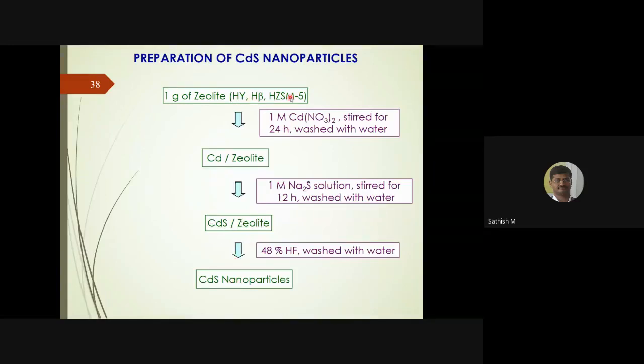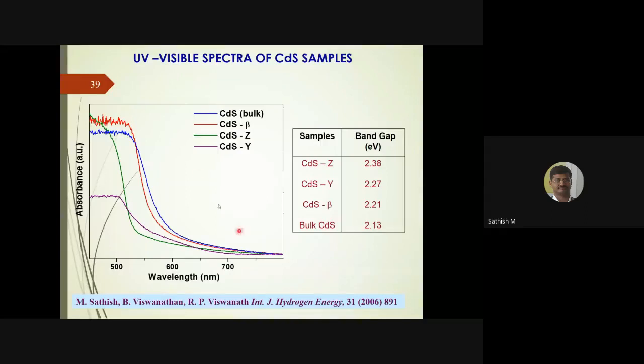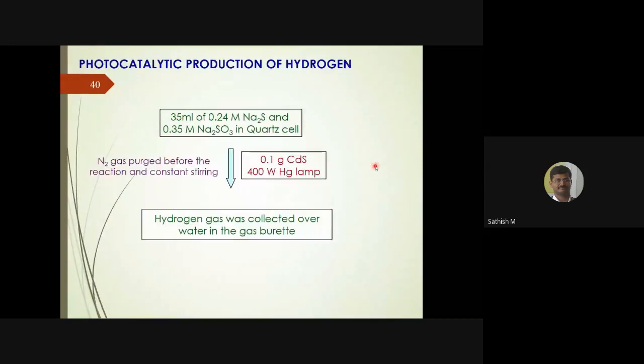So that cadmium sulfide nanoparticle you could get. Depending on the pore size or pore volume, you could make different, uniform sizes of cadmium sulfide. When you have a nanoparticle, the band gap between your valence band and conduction band increases. Because of this, you could do more oxidation and reduction reactions. Of course, you have to compromise in the light absorption. There may be some small variation in this. For bulk cadmium sulfide, the band gap is 2.13, whereas for this nano-sized catalyst, it varies to 2.21, 2.2 or 2.38.